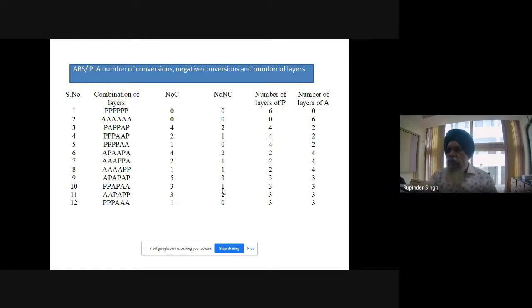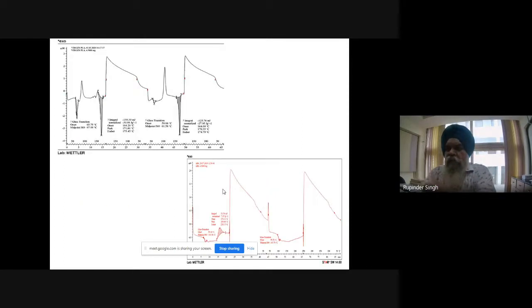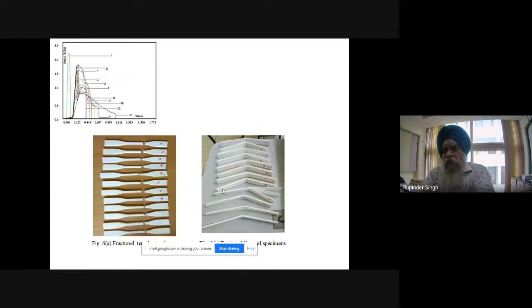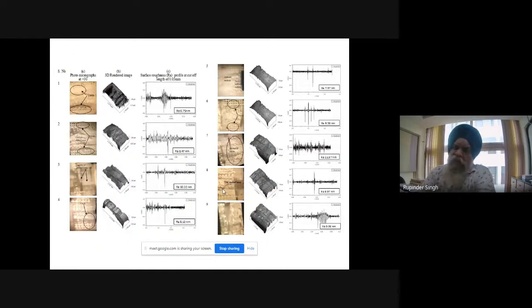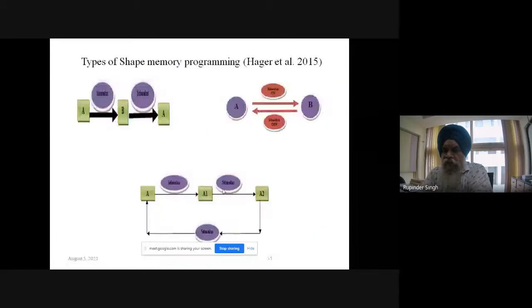So if we follow this route, we will have a better substrate for our samples. We try to correlate it with their thermal properties, with their flexural properties, and we try to break those samples and see how this will behave. And we also try to correlate this with their microstructure and their porosity value and the surface finish value, because these are really important for my sensor application, right? So basically converting, calculating the number of A's, number of P's, number of negative conversions and number of conversions, this helps me in controlling the behavior of my material, right?